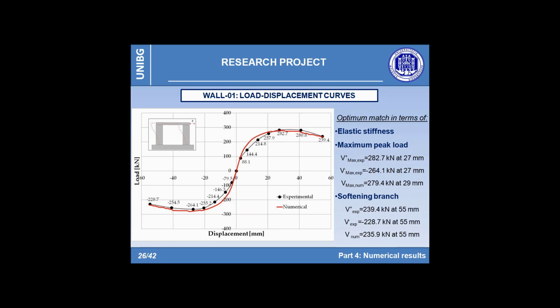Regarding the softening branch, after the peak load, a key role is played by the parameter of the compressive fracture energy that affects the ductility level provided by the structure. In this case, a value of 50 kJ per square meter has proven to be reliable. However, for wall 1, the seismic response seems to be very symmetric, and overall the capacity curve obtained from the finite element analysis is able to simulate with high approximation the structural behavior exhibited by the specimen.